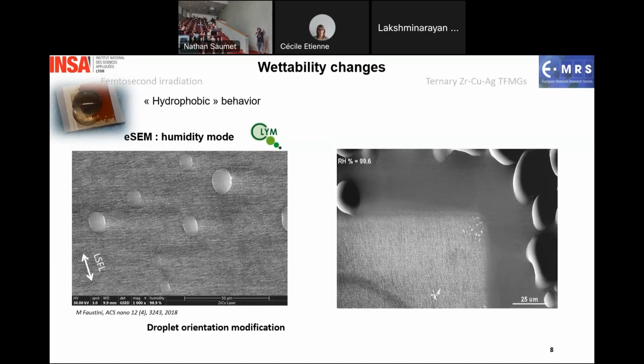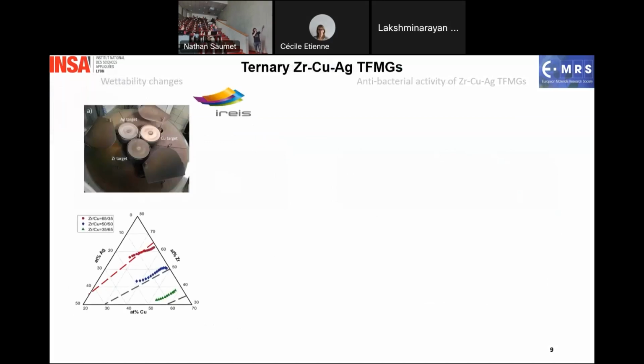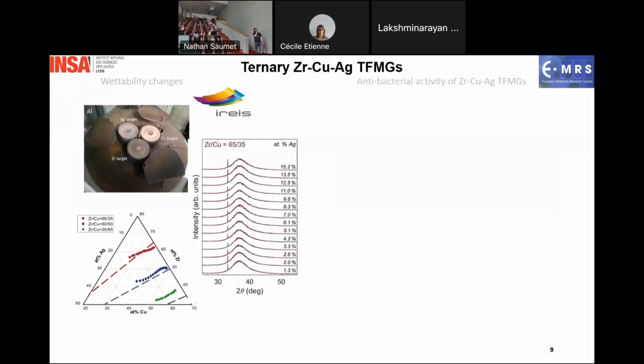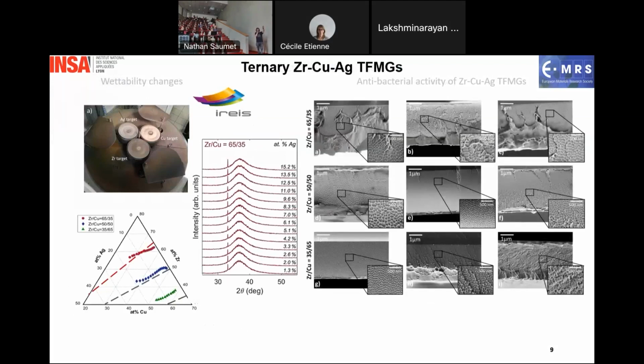To also check the chemical effect on the bacteriological behavior, we made ternary thin film metallic glasses by adding silver to our zirconium copper thin films, made as arrays with a lot of compositions of the thin films. We saw that for each composition, the XRD measurement shows amorphous characteristics, and also when cutting the thin film, we saw the vein-like pattern, so they are amorphous and they are metallic glasses.